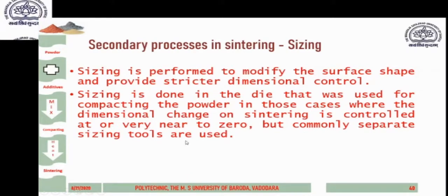Generally, another die will be used because whenever it is a green compact, the shape size will be quite small, slightly larger. As the heating is done, sintering is done, there are chances that the green compact may shrink in, so that small amount of dimensional tolerance on the negative side will be available.